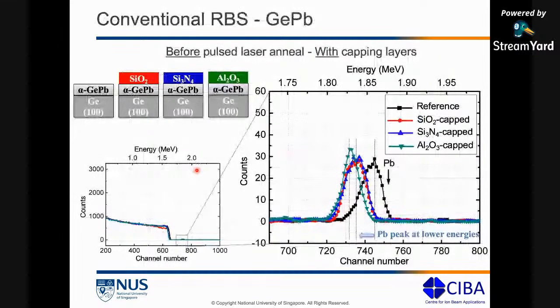So to start with, when we first got the samples, we just did a conventional RBS on these samples. So we had 4 samples. We started with the bare germanium lead. This was the reference sample, and then we had these 3 capped samples: silicon oxide, silicon nitride, and aluminum oxide. We did a conventional RBS. So this is a typical RBS spectrum.